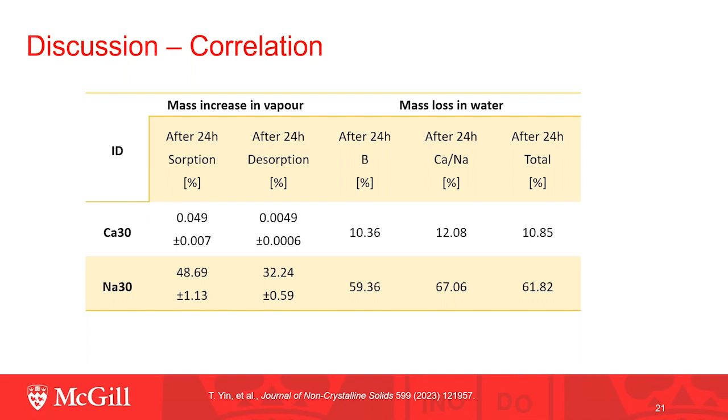Moreover, it can be found that the more vapor sorption weight change corresponds to the more weight loss in the water, indicating the faster vapor reaction corresponds to faster water reaction. This demonstrated the correlation between vapor sorption and dissolution reaction rates.